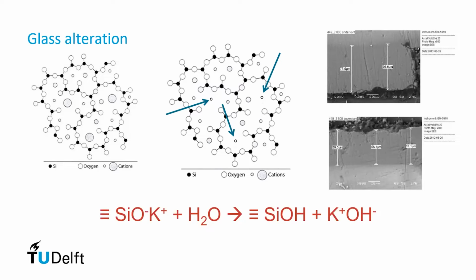And this is an important feature because initially it may not look like the glass has changed, but when you change the environment, for example, when it's stored in a dry environment, the water that is incorporated in this layer may evaporate, causing a shrinkage of the top layer, resulting in the crack formation.